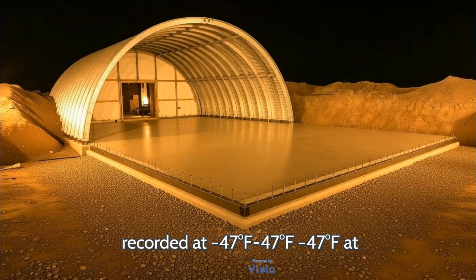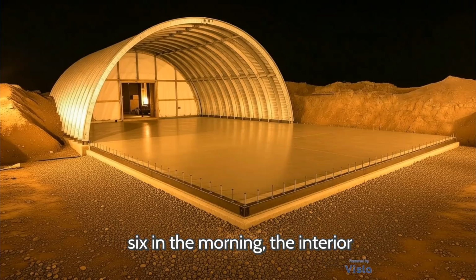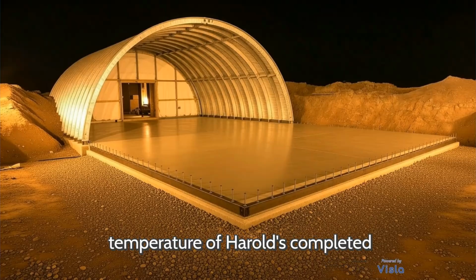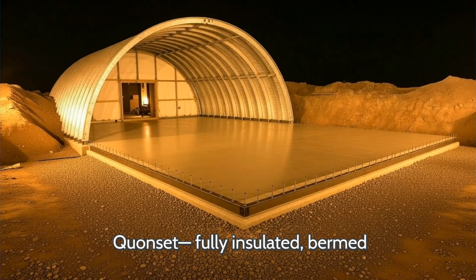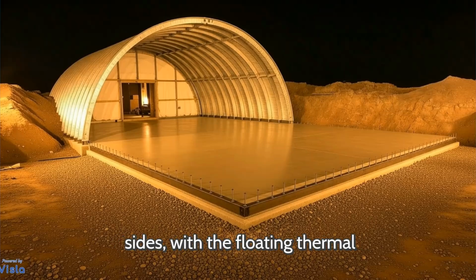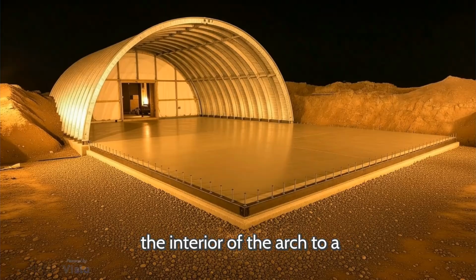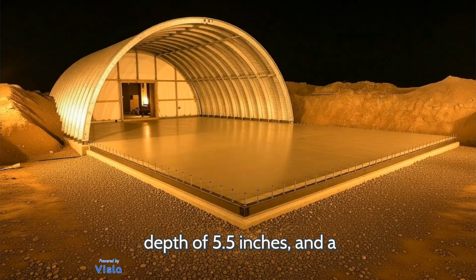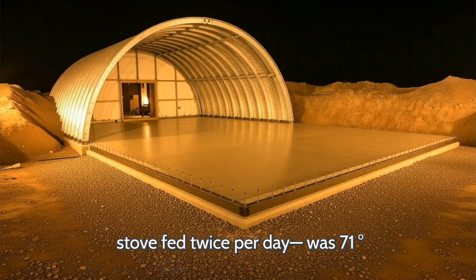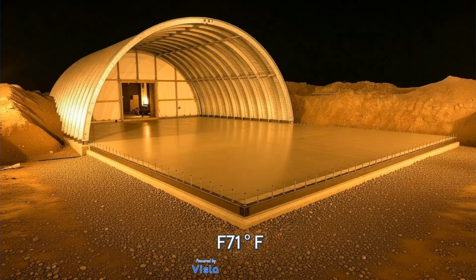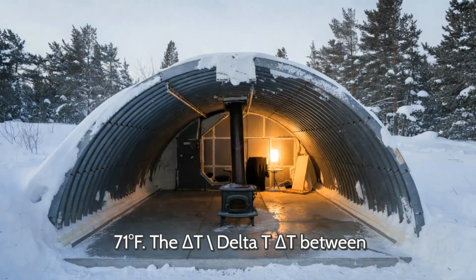At the time of our most recent visit, in February of this year, the exterior air temperature was recorded at minus 47 degrees Fahrenheit at 6 in the morning. The interior temperature of Harold's completed Quonset, fully insulated, bermed to a height of 52 inches on 3 sides, with a floating thermal slab, closed-cell spray foam on the interior of the arch to a depth of 5.5 inches, and a central wood-burning masonry stove fed twice per day, was 71 degrees Fahrenheit.